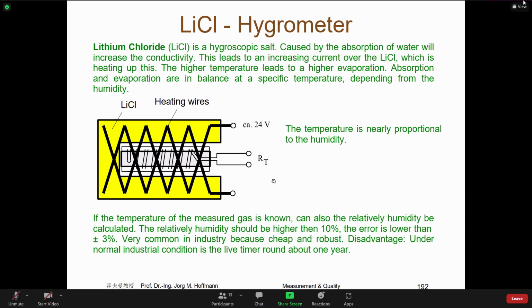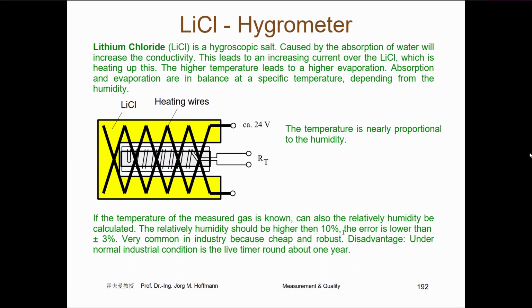These sensors are very cheap, but yeah, it is written that the humidity should be higher than 10% because when you have no current here, you need a minimum of current to heat it up, and so it works when it is higher than 10%, but 10% is very low. And the error is lower than plus minus 3%. That is for industrial applications a very normal value, plus minus 3%. Many sensors are in this range. And therefore, because the sensor is very cheap and very robust, it is often used in the industry.